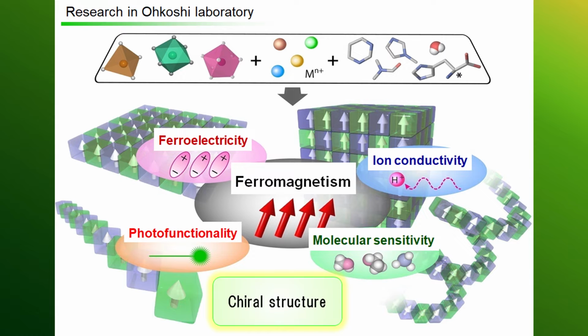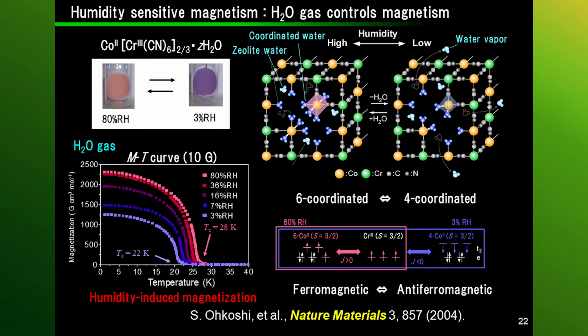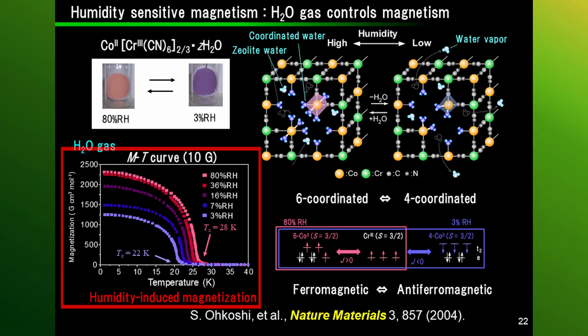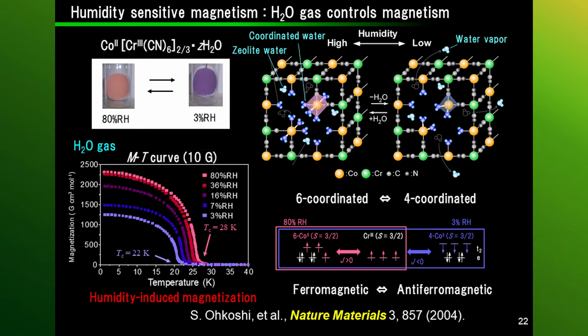Everybody must have seen a magnet, but you would not expect that humidity affects the properties of a magnet. You may think of performance change and development of rust, but not changes in material property. This material is made using cobalt chromium metal ions, bonded with cyanide, and it changes color with humidity. This is a material with magnet properties, but the magnet temperature curve of the material demonstrates change in the level of magnetization between 22K and 28K, depending on the level of humidity.